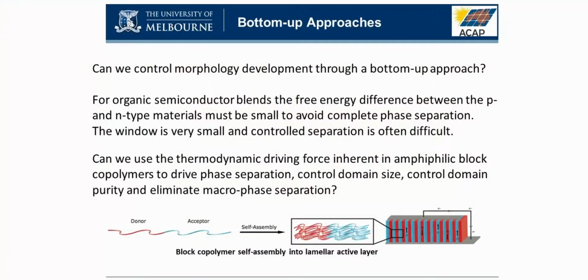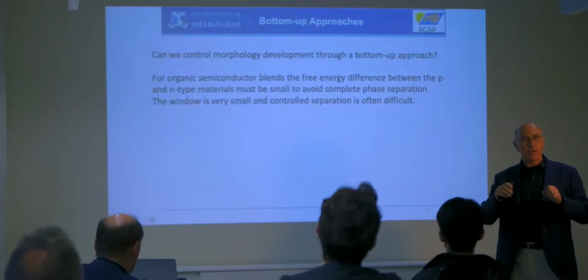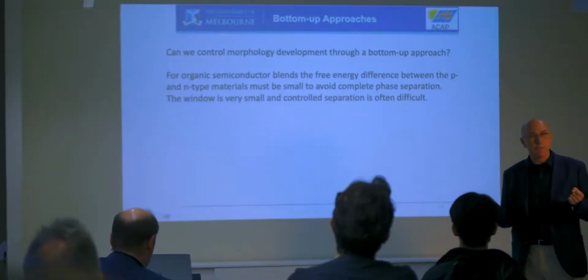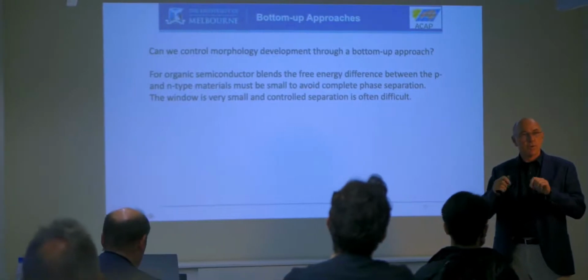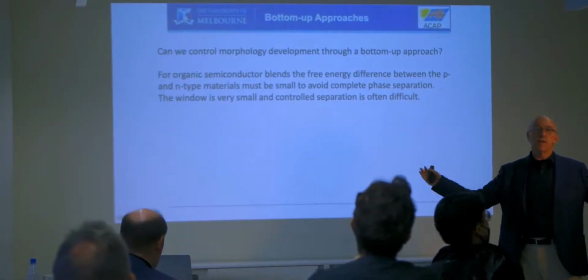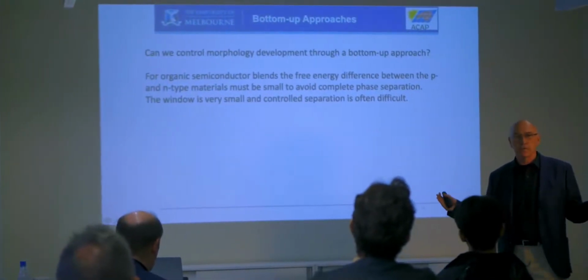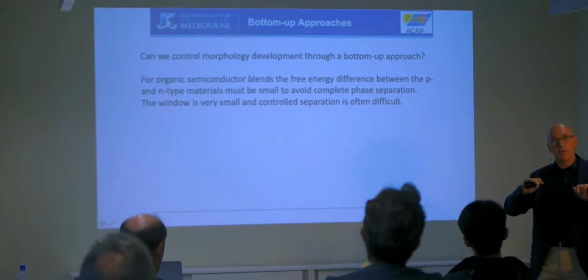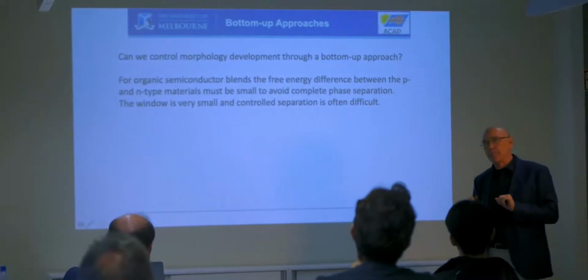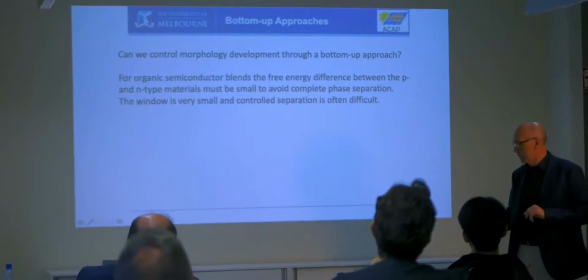Okay, and so for organic semiconductors, the issue that we have is that when we are making this blend, we really need to have the free energy of the two materials very, very close. Because if we don't have it close, when we try to make this junction from the blend of the two materials, they'll phase separate, and therefore we won't get a very good device. So we actually have to have a very, very similar free energy of the two materials.